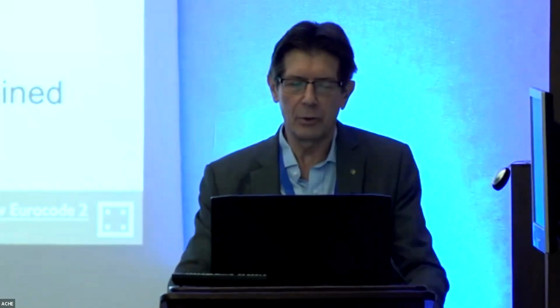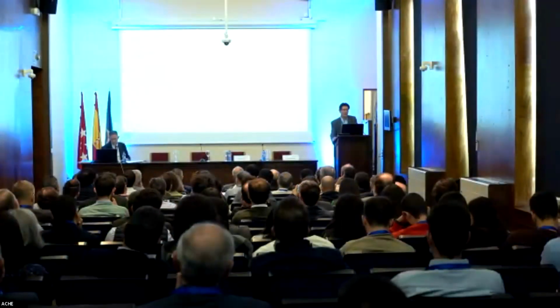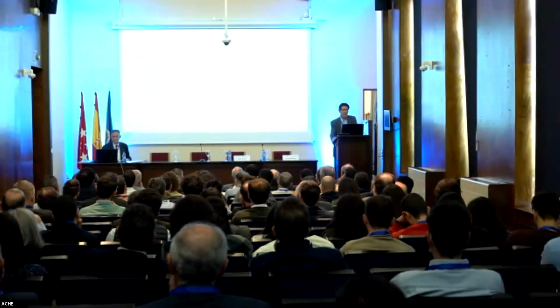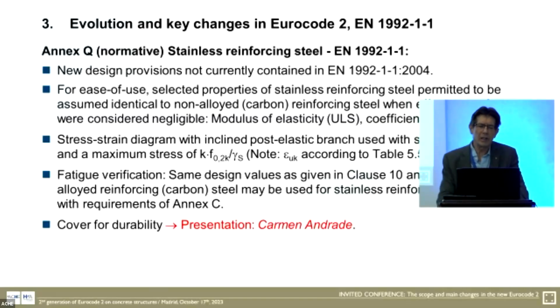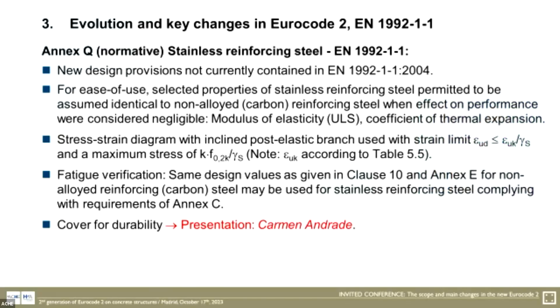For pre-stressed concrete, it's basically the same, but we do not have the lowest category where you can use the same properties as for normal concrete. You see again here the table where we give all these changes per clause where there is a change. So again, very easy to find and to implement. Annex Q, stainless steel reinforcing steel, that's also new information. We recognize that the properties of stainless steel are different to the properties of non-alloyed steel, sometimes more, sometimes less. But we also found that at least for ULS design models, these differences are not really relevant. They are negligible, and therefore we permit, certainly for ULS, that you can use the same properties for stainless steel as you use for non-alloyed reinforcing steel,